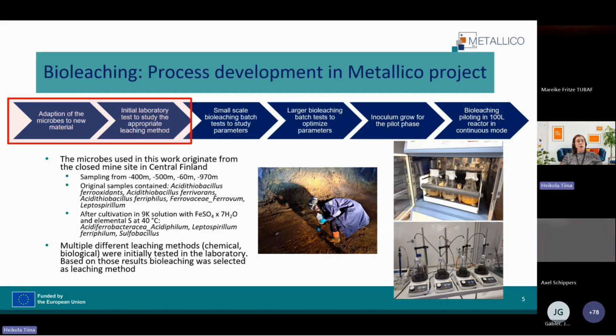And now I will move on to the kind of process development in the METALLICO project, concentrating on the bioleaching. So we started the work with the sampling trip to a closed mine site in central Finland, and we collected samples from different depths and did the microbiological analysis afterwards in the lab. The microbes were first cultivated and then adapted to a new material gradually. And after the adaptation, multiple different leaching tests were performed, both chemical and biological, in the small laboratory tests. And based on those results, bioleaching was selected as the leaching method for the METALLICO process.